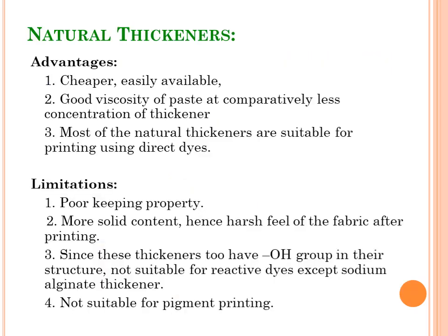Friends, we have seen the essential requirements of thickener. Now let us see the advantages and limitations of each type of thickener. In case of natural thickeners, the advantages are that they are cheaper and easily available. The second advantage is good viscosity of the paste at comparatively less concentration of thickener. Generally, in case of natural thickeners, 6 to 7% concentration gives us good print viscosity. So at comparatively less concentration, we can get the desired viscosity of the paste.